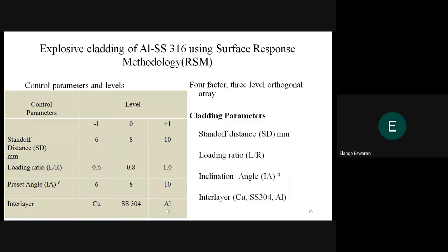The next one is the interface strength in explosive cladding. In explosive cladding, the interface strength and the characteristics are dictated by the optimal selection of operational parameters via standoff distance, loading ratio, inclination angle, and the interlayer. The optimal selection of process parameters results in a higher tensile strength. However, the strength will be reduced if the operational parameters are not selected properly.